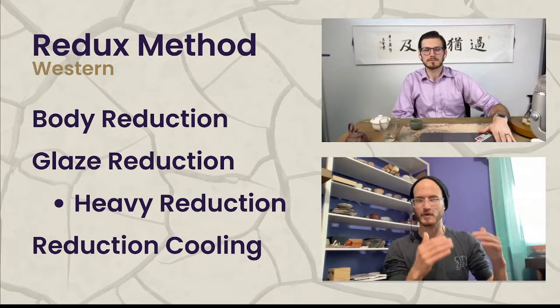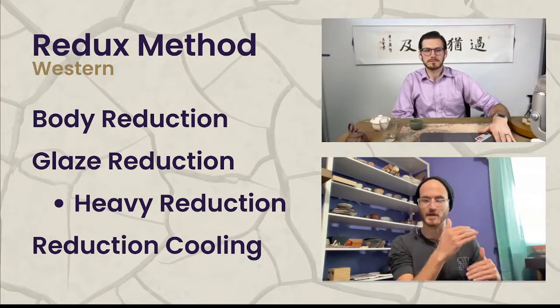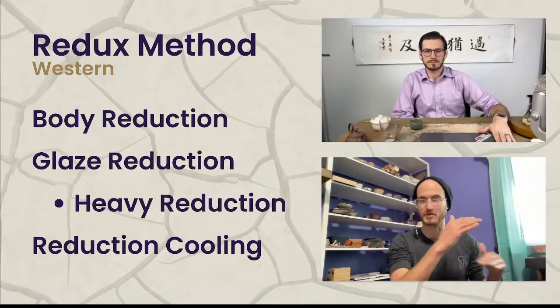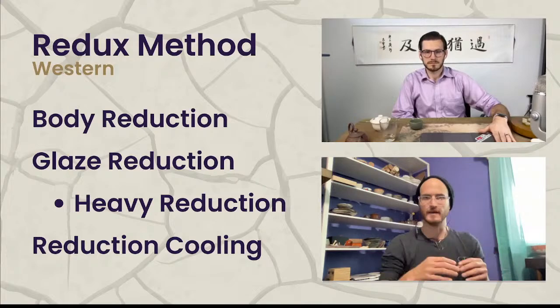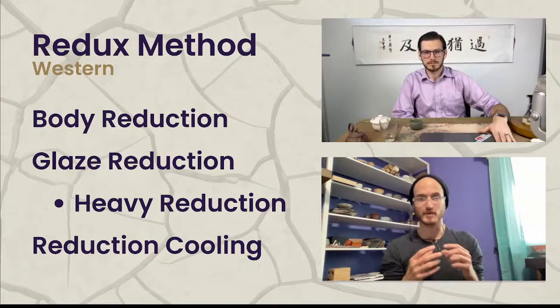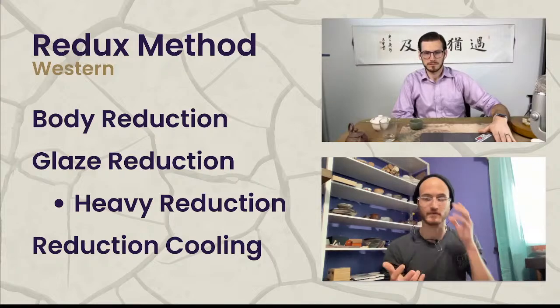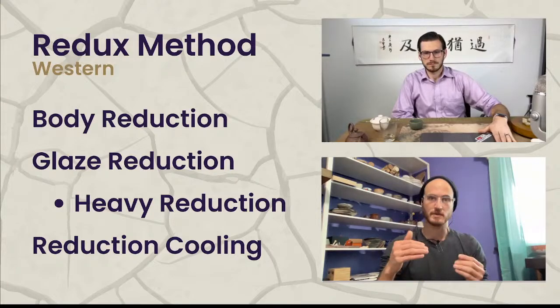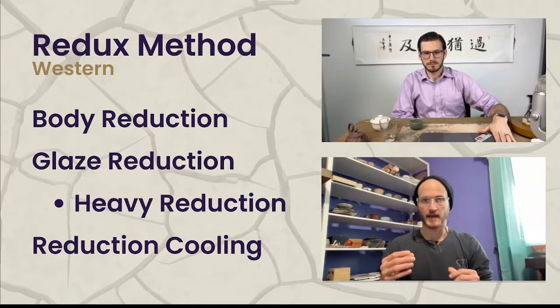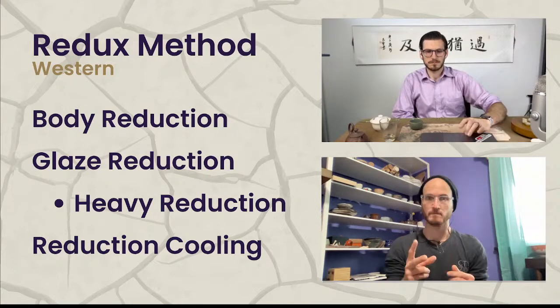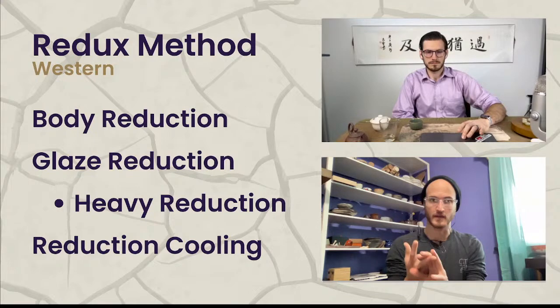There are certain points where you really don't want to go fast through temperatures, but for the first 100 to 200 degrees C, really you're safe as far as the structure of the clay. But it's an aesthetic and stylistic decision, right? If you're going to crash cool, it's because you want a certain effect. And the main two are texture and color.